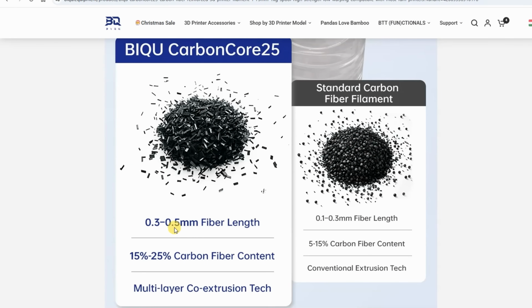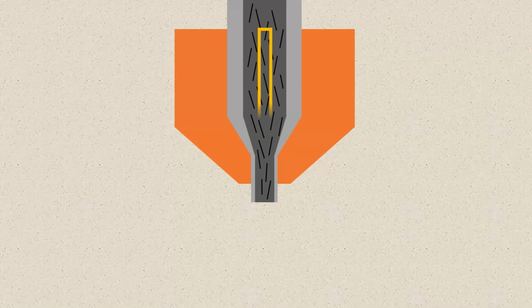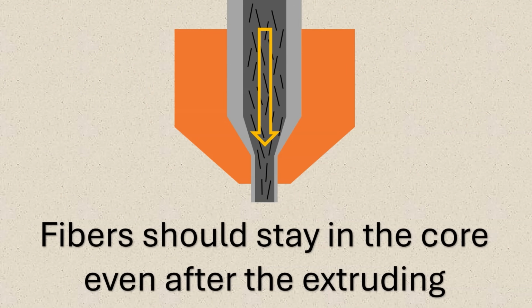Additional information from the website. The size of these chopped fibers is between 0.3 and 0.5 millimeters. This is bigger than average, and with normal filaments I would worry about the clogging of the nozzle if I use 0.4 mm size. But this is core filament and these fibers should stay inside. The flow is laminar, and I even asked BIQU and they confirmed that we can use 0.4 mm nozzle.